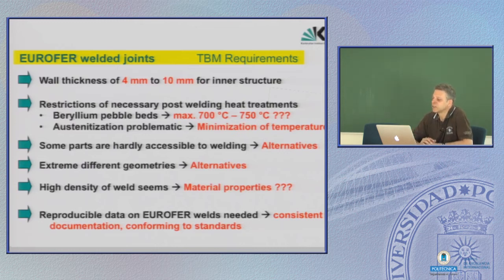This is the restriction. So for especially these final welds, which will close the breeding boxes, you are restricted to only a tempering treatment after weld. And this means also you cannot perform this austenitization treatment, and therefore we made some general investigations: what is the lowest possible effective austenitization treatment and what is the lowest possible tempering treatment for such welds.